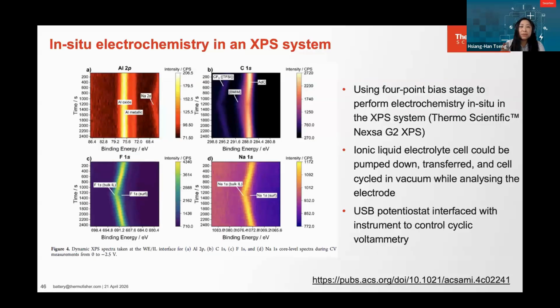And you can see that when we apply the bias, we introduce a shift for the electrolyte components, but not necessarily on those elements bound to the electrode. So when the cell is being cycled, it's very clear here. You can see the intensities for the sodium and fluorine surface components appear to increase, and which are actually irreversibly bound to the electrolyte.